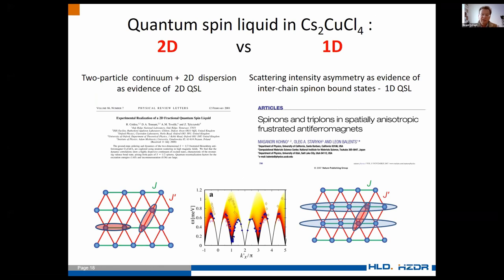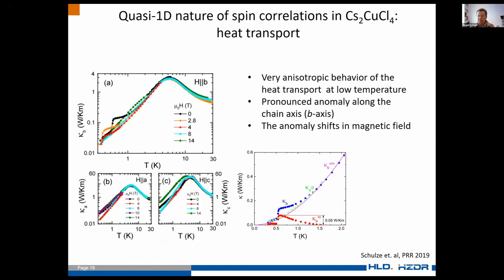Initially, it was determined to be a two-dimensional quantum spin liquid. But in reality, if you look at the inelastic neutron scattering data, you would see that there are some bound states, and this bound state is not typical for 2D. What happens here is just because of frustration. This material can be regarded as a system of one-half quantum spin chains, and because of the interaction between these chains, there are spinons. It's not a 2D quantum spin liquid, it is a 1D spin liquid.